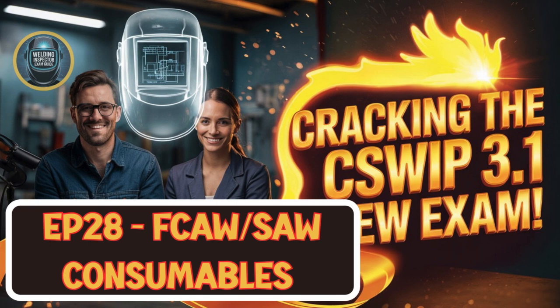And rule number 1, different types of fluxes should never be mixed unless it's a specific controlled blend recommended by the manufacturer. And one of the sort of unsung heroes in ensuring all this happens correctly are the classification systems. Standards like BS EN ISO 14171 or the American AWS A5.17. These are essential tools. They help welders and engineers identify these complex combinations by providing specific values for tensile and impact properties, the flux type, fused, agglomerated, basic, acidic, etc., and the wire's chemical composition. This ensures that the right consumable combination is selected for the specific job, guaranteeing performance, integrity, and preventing potentially disastrous mistakes down the line. It's like a blueprint for predictable results.